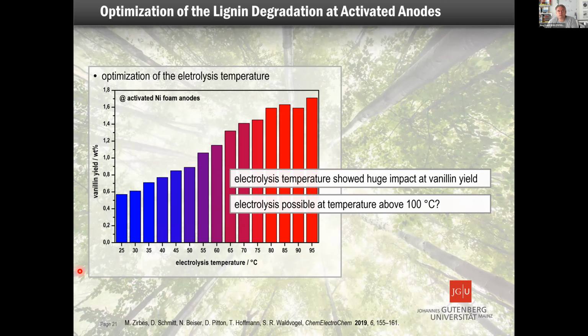Then we just have to go to the other parameters, and it turns out that a higher temperature seems to be better. What is the reason for that? The lignin particle is a little bit like a gummy piece, and at higher temperature it becomes a little bit more floppy, and then the product is more liberated. The question is, can you go in the electrolysis over 100 degrees?